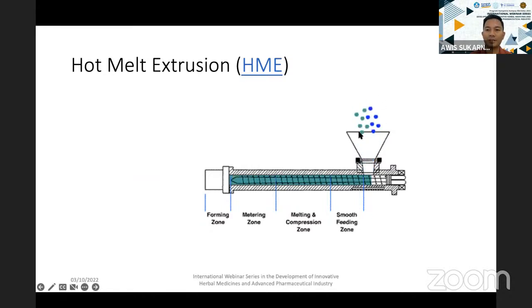So in order for you to know what is the degradation point of the active ingredient that you have, the first thing you can use is the DSC or the TGA. Differential scanning calorimetry, or you can use thermogravimetric analysis. So by using these two instruments, you can determine what the degradation point is. The degradation point is basically where you burn the sample. So there is no turning back at that point. Once you exceed the degradation point, your sample is already ruined, so you cannot use the sample. So you just take a small amount of the active ingredient that you're going to use, then check what the degradation point of the sample is before you use it in hot melt extrusion.